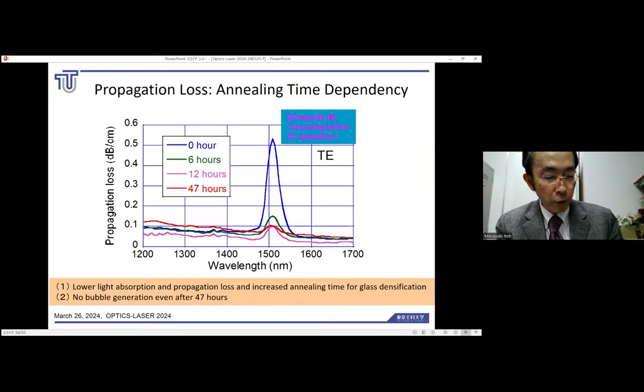This shows the relationship between wavelengths and propagation loss for waveguide B, which is heat treated before overcladding is deposited. We found that there is a significant change in this relationship when the heat treatment time is varied. The absorption of the NH group at around 1500 nanometer can be reduced by increasing the heat treatment time to 6, 12, and 47 hours, as shown in this figure. In other words, longer heat treatment time reduces the absorption of NH groups and propagation loss. There was no bubble formation after 47 hours of heat treatment. These two points were confirmed.